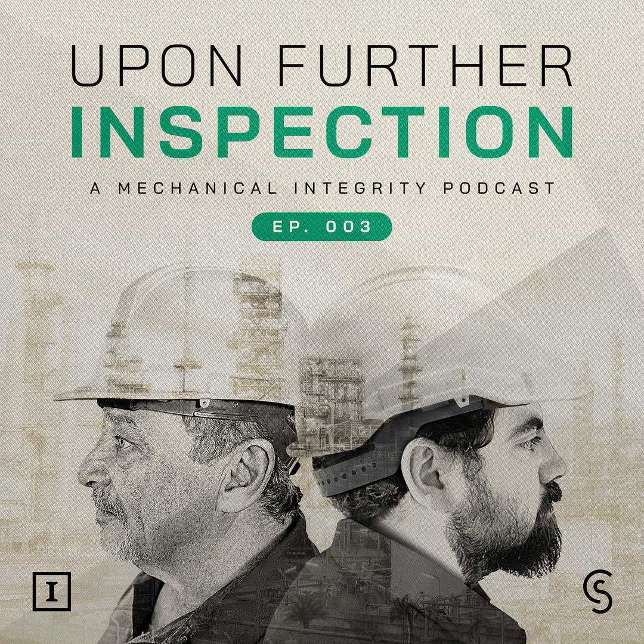There was lab testing being done then, but it was growing because we were really trying to understand the phenomena well. And what triggered the original lab testing was the failure of the Lemont, Illinois contactor that killed, I can't remember if it was 17 people or whatever in Chicago back in the 80s, the late 80s. Mm-hmm. And that just fueled this even more. But there's a phenomenon called sulfide stress cracking, which goes through wall much quicker than just HIC-SOHIC on its own. And the reason for the sulfide stress cracking is weld hardness zones.